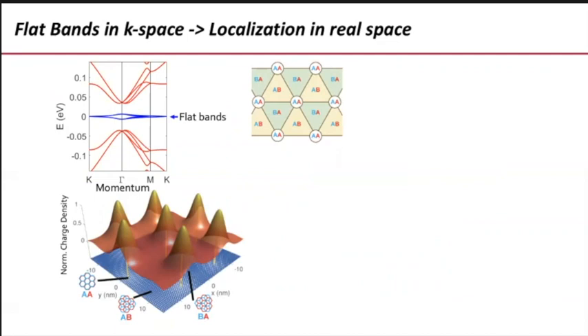And if you put electrons in these flat bands and you try to go back to real space and see where they like to sit, it turns out electrons in these flat bands like to sit in certain regions, which we call AA stacking, where locally all of the carbon atoms on the two layers are on top of each other. Now, in reality, there's a small twist angle, right? So there is a shift in registry as you move in the Moiré pattern. So there are regions of AB and BA stacking, where A and B refer to the two sublattices of the honeycomb graphene lattice. And in these regions, the electrons do not like to be. So schematically, magic angle twisted bilayer graphene looks like this. You have this Moiré pattern where you have these AA regions where the electrons like to sit, and these AB and BA regions where the electrons do not like to be too much.